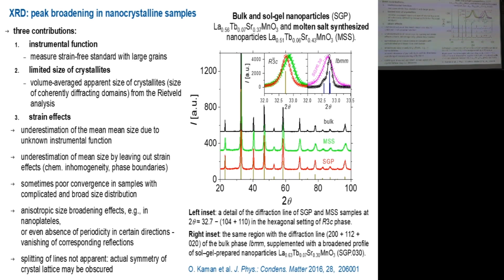However, if you prepare some nanoparticles of small size, and if you consider the line broadening, this fine structure, these asymmetries might be completely obscured. So for nanoparticles, it might be difficult to analyze some distortions, some deviations from some simple symmetry. However, in this case, these 2 samples are rhombohedral or trigonal.